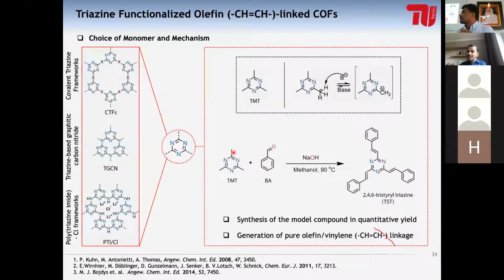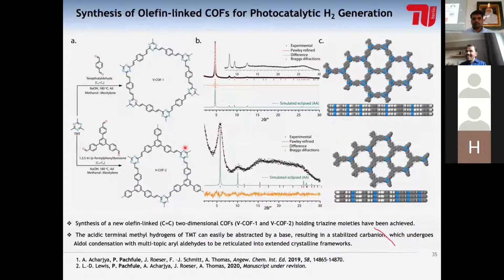So by using such a small molecule, you can synthesize the monomer, which can be extended into 3 dimensions. So how can we do that? This is really important: just a small molecule can be extended into 3 dimensions. And here, trimethyl triazine, having this active CH3 group, was converted into the framework by reacting with terephthaldehyde or C3 symmetric 1,3,5-triformylbenzene, which is important for any particular application. Here you see these are the triazine moieties coordinated to the phenyl ring through just a carbon-carbon double bond, very similar to the PPV I showed in the previous slide.